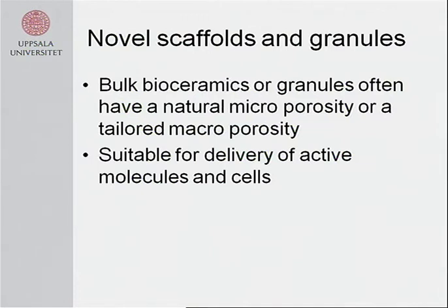When it comes to scaffolds and granules and drug delivery, bulk bioceramics or granules, these types of bioceramics have a natural porosity, with microporosity, which is very good for loading and slow release of drugs. But you can also tailor them to have a macroporosity for delivery of cells. But as Sam said, it's difficult to keep the cells within the pore structure. They migrate away, or usually the cell delivery from bioceramics is a difficult task. It's much easier technically to deliver active molecules.